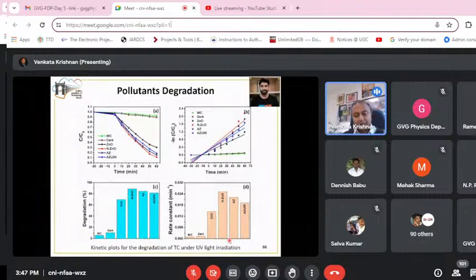Then we again did the same experiment under UV light radiation, and here another sample, the n-doped ZnO, gave the best photocatalytic activity. This indicates that the NZnO, having an appropriate band gap in the UV range, is the active semiconducting material for this purpose.